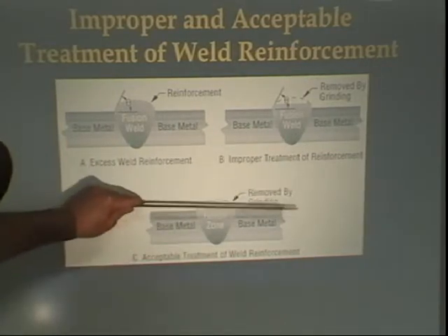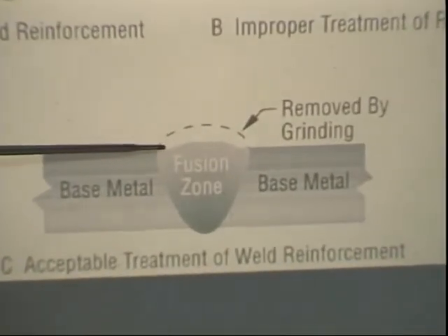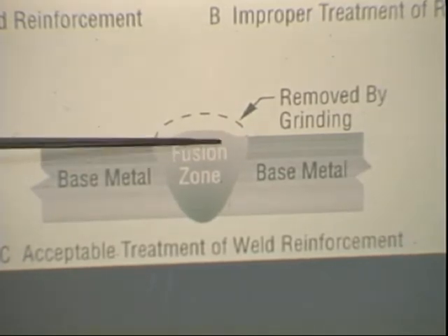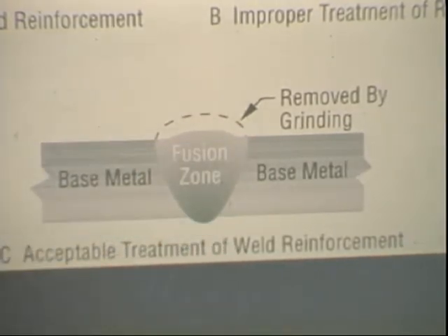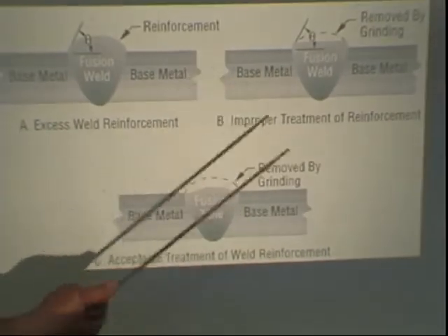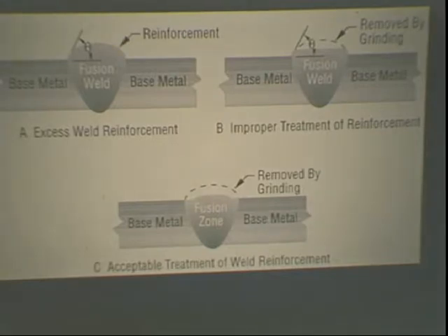So our last picture down here shows us how it's properly been changed, how they've ground into it a little bit and they've transitioned it a little more smoothly. So now that stress riser has been removed. So if you have to encounter something like this, make sure that whoever's doing the repair doesn't just knock off the top of it, because that does nothing to remove that stress riser.